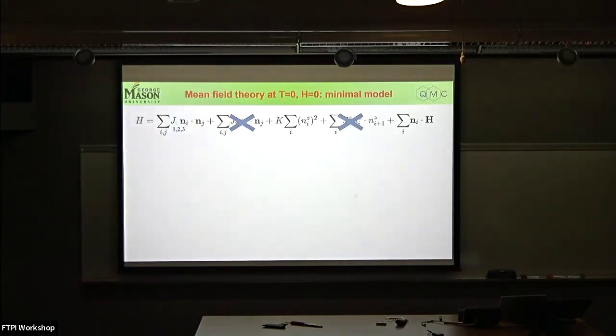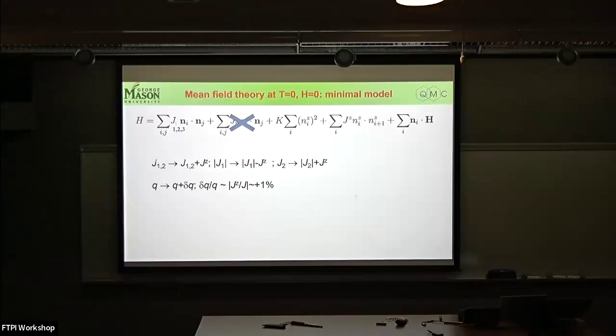All right. So this is this view. Now I'm gradually unsimplifying the model. Now I'm adding this Ising interaction, and I can tell you why. The reason is that the pitch of the spiral is determined by the ratios of J1, J2, and J3, particularly J1 and J2. Now, single ion anisotropy does not affect the spiral pitch. So the question why they have a couple of percentage change in the spiral wave vector was unclear until I did the calculation and found that this term is comparable and actually twice larger than single site anisotropy. Interestingly, single site is easy axis, but Ising anisotropy is easy plane and it's about twice larger.